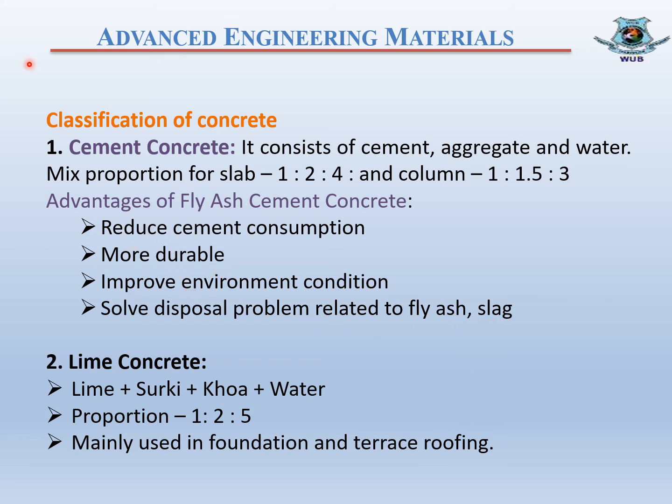Lime concrete. Lime concrete consists of lime, surki, koa or stones and water in the proportion of 1:2:5 unless otherwise specified. The koa or stones should be soaked thoroughly in water before mixing. These are mainly used in foundation and terrace roofing.